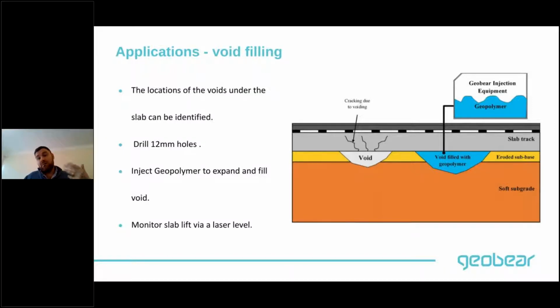We can actually keep injecting geopolymers to the point that we start generating high lifting pressures, and these lifting pressures will start lifting the slab. We can control that lifting by using laser level monitoring, for example, so you can lift it to the desired position. So you're not only filling the voids, but you also have the ability to lift the slab to the desired position and restore your track geometry.